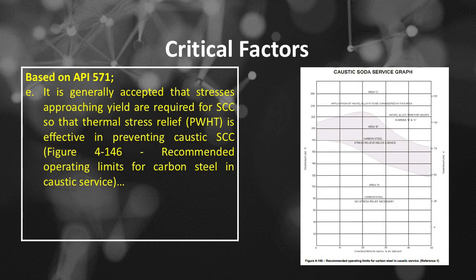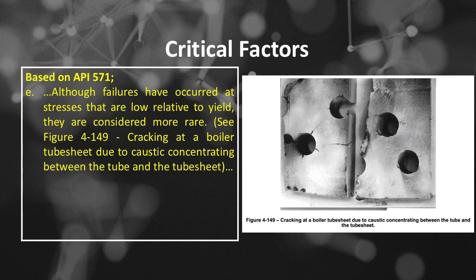Number E, it is generally accepted that stresses approaching yield are required for SCC, so thermal stress relief or PWHT is effective in preventing caustic SCC. See Figure 4-146, recommended operating limits for carbon steel in caustic service. Although failures have occurred at stresses that are low relative to yield, they are considered more rare.